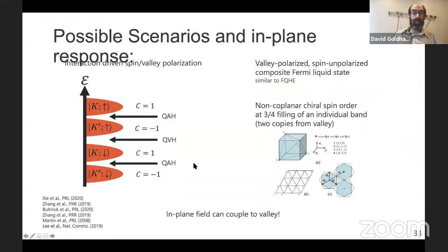I mentioned a very simple scenario that we have polarization and we can fill 3 of the 4 polarized bands and not the 4th, but there's a proliferation of other suggestions for what could happen, some of them quite exotic, analogies to a composite Fermi liquid state suggested by Senthil and co-workers, something that I don't think has necessarily been suggested for this case. But you can get something that looks orbital that actually comes out of spins that are canted and that go around sweeping out a solid angle when you go around a plaquette. And so there are all kinds of things that could give this sort of behavior.